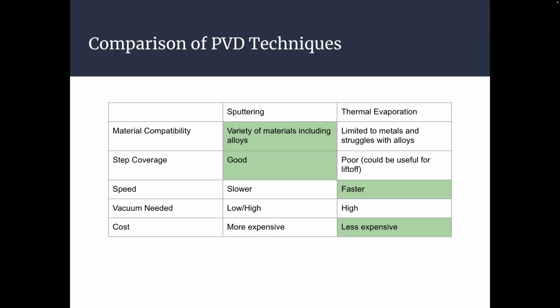And then we all like some good comparisons. We have our two simplest PVD techniques, sputtering and thermal evaporation. Sputtering tends to be more accommodating in terms of the materials that you can use, whereas with thermal evaporation you're restricted to metals, and it also struggles with alloys, whereas with sputtering you can do alloys, you can do organics, you can do a bunch. The step coverage is also better for sputtering, whereas with thermal evaporation the step coverage is worse. This is related to the vacuum needed. Sputtering could be done in low or high vacuum, whereas thermal evaporation requires a higher vacuum. Translated to pressures, thermal evaporation needs an even lower pressure than sputtering.